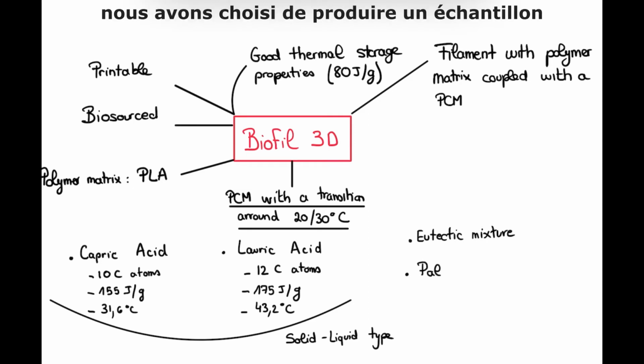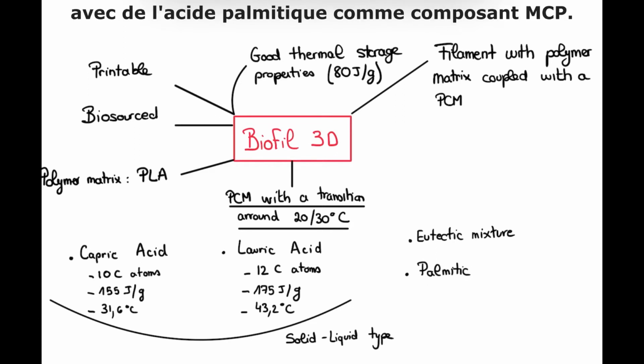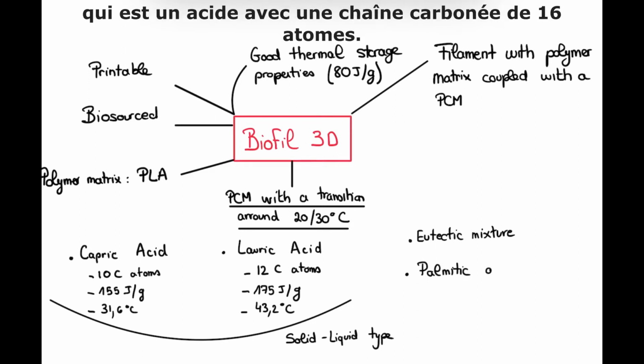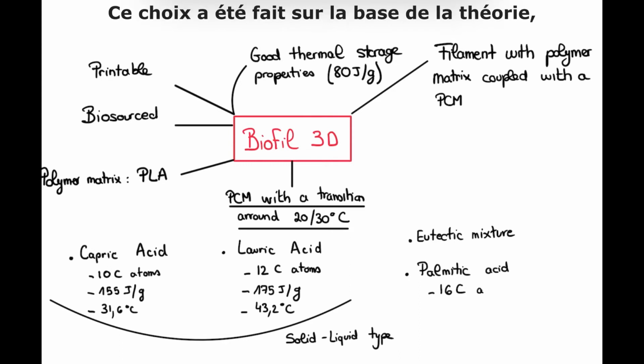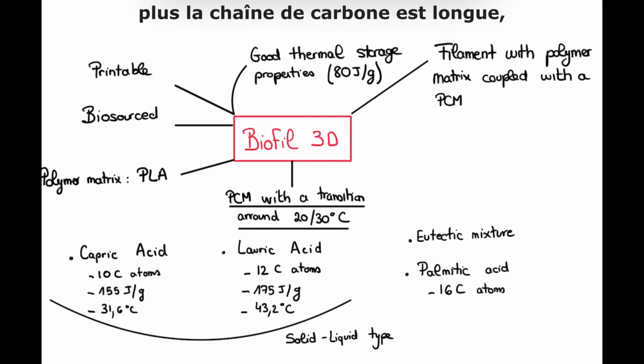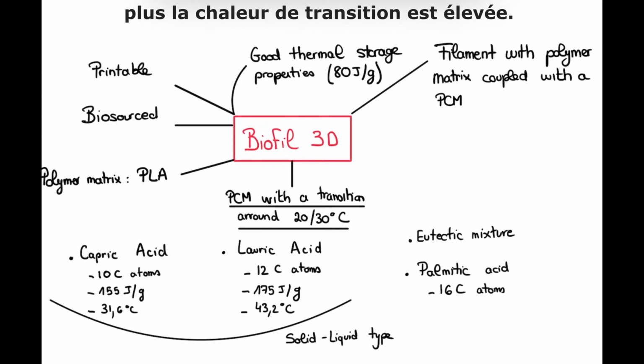On the side, we chose to produce a sample with palmitic acid as the PCM component, which is an acid with a carbon chain of 16 atoms. This choice was made on the theory that the longer the carbon chain, the higher the heat of transition.